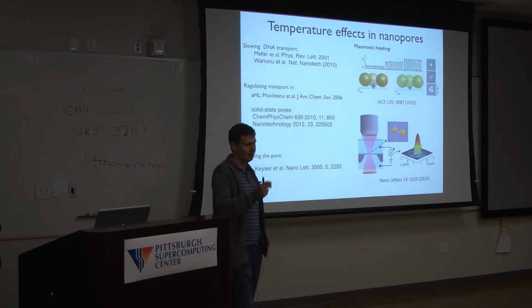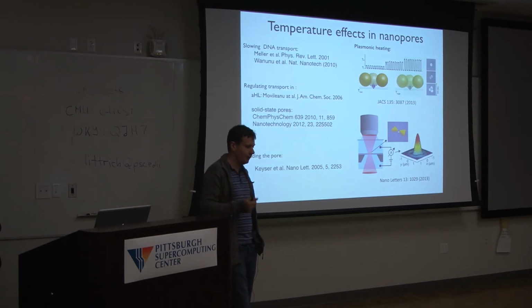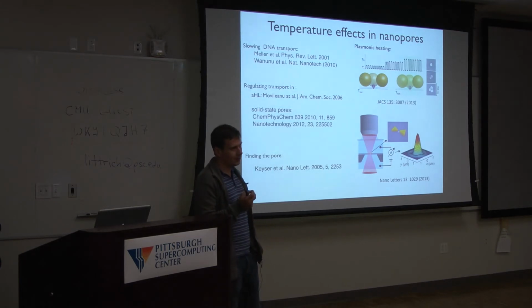You can actually melt them in solution. So you have particles in water, you can shine a laser on it, and they will melt and still be in solution. And then you could switch it off, and basically within a few nanoseconds they will solidify. Because they're so small, this process of heating and cooling is very rapid. And you can do it with light, and that's great because light you can modulate very fast. You don't have any capacitance problems that you have with the electric field.